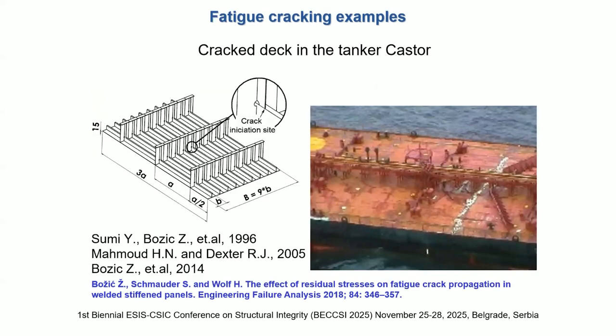Similar situation we have with ship structure. What you can see here is the deck structure turned upside down, and you have different panels in longitudinal directions, and you have also bulkheads every 5 meters. So these details are produced by welding. So there are stress concentrations due to geometrical discontinuities and residual stresses. And cracks initiate here, similar to the Aloha example, in several locations.